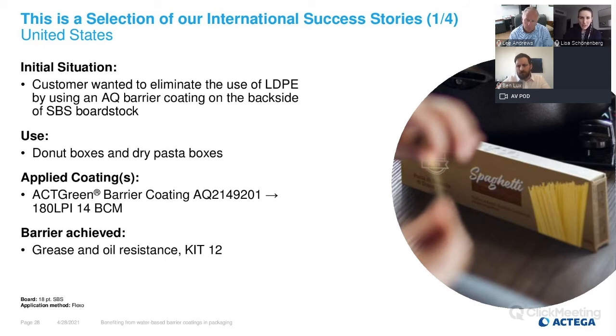To underline ACTEGA's achievement with barrier coatings so far, we would like to share success stories from all around the globe. A customer of ours in the United States wanted to replace PE laminated board by using a barrier coating on the backside of SBS board stock. Especially for the production of folding boxes for fresh bakery products like donuts, but also dry pasta, the main requirement was a very pronounced grease and oil barrier, which we were able to realize with one of our grease barrier coatings. They also tested this coating on various other substrates, including kraft cardboard, for instance, and are fully convinced of the barrier properties.